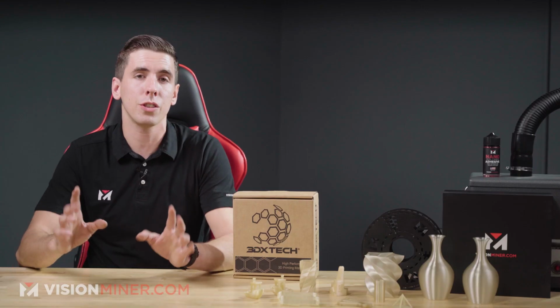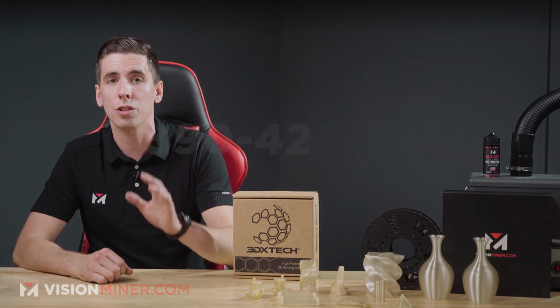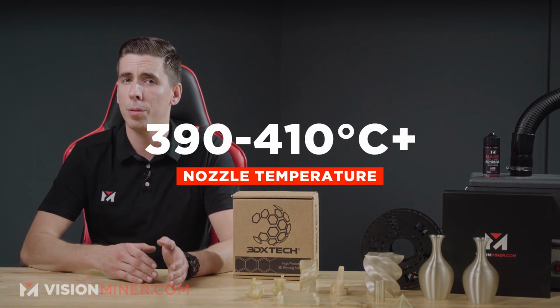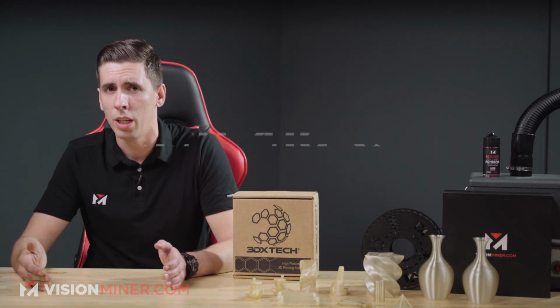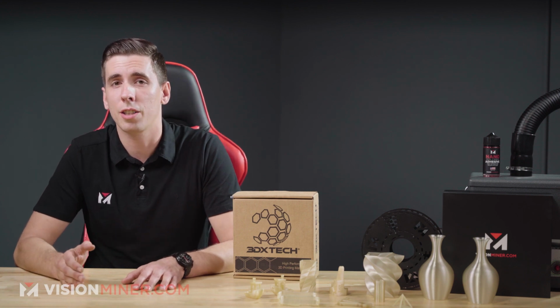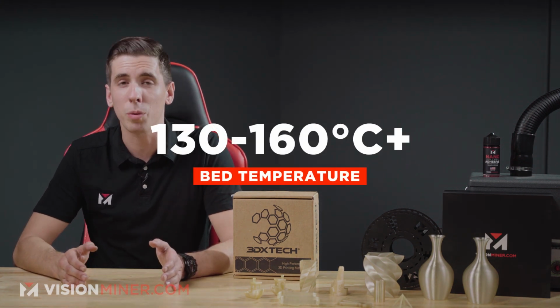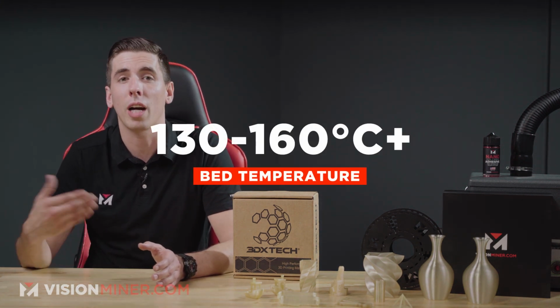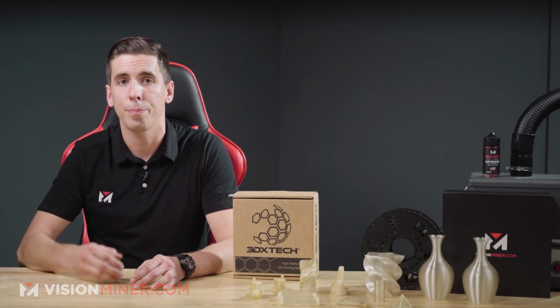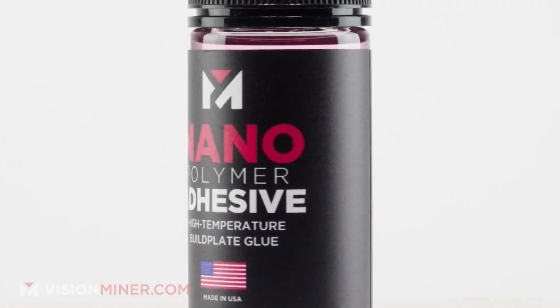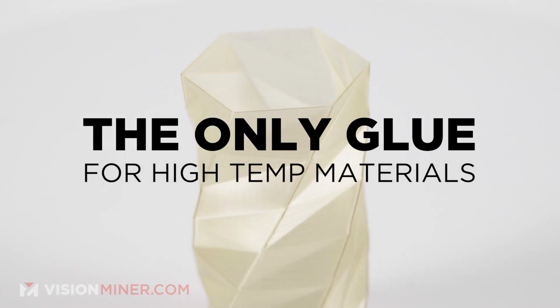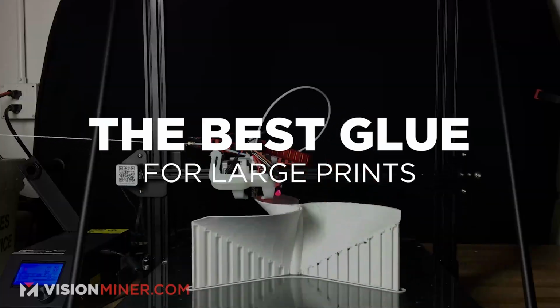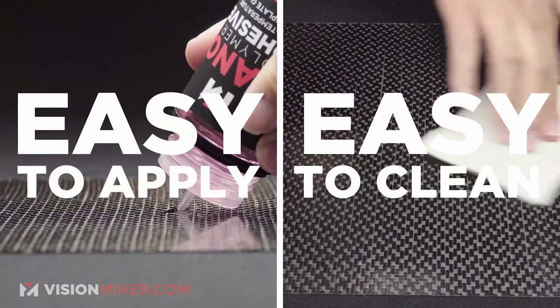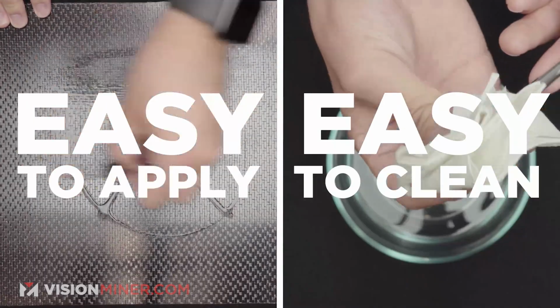So what kind of machine do you need to print this filament? Firstly, your nozzle is going to have to go to at least 390 Celsius, preferably up to 410 or more. The bed on your machine is going to need to go to at least 130, but we usually print around 160 or higher if the machine is capable of that. As far as adhesives on the build plate, our nanopolymer adhesive works great for this material. It's one of the original materials we actually designed the stuff for, so as long as you got that, you don't even need to use brims.